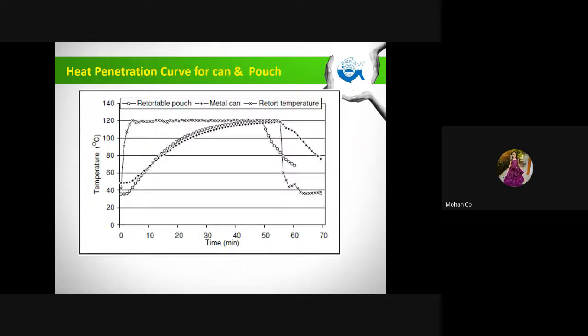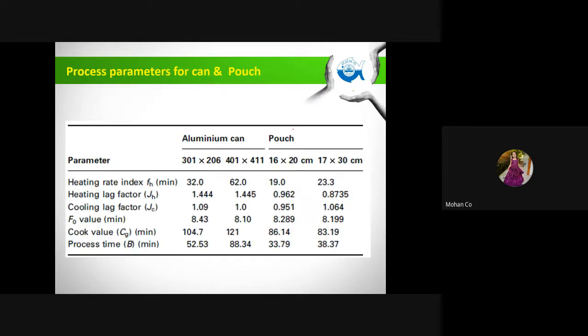So this is the heat penetration curve for a can and pouch of the same pack weight. You can see cooling has started earlier in the pouch compared to the metal can. If you are using the same pack weight for the can and pouch, this is for a 750 gram product. This is a shrimp based product. It has taken almost 52 minutes in the aluminum cans for 750 gram, whereas in the case of retort pouches it has taken only 34 minutes.